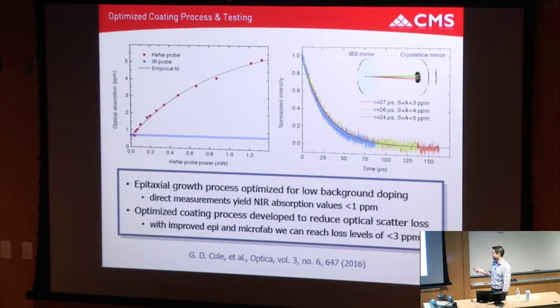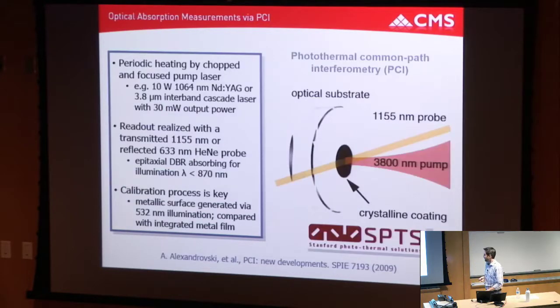And then we've built up some very cool capabilities for scanning ring down, where we can take the optic, raster it, tip tilt it, and hold the fundamental mode of a linear cavity as a function of position, and really map out the optical losses in ring down. So here's this PCI technique. It's very cool. I just thought I'd throw this out there.